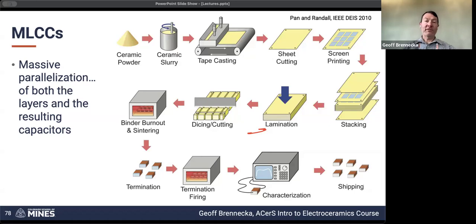And then we throw it in the furnace, just like everything else we do in ceramic processing. There's a furnace step of some sort. So in this case, we're going to burn out the binder as slowly as necessary, because if we just throw it in and heat it up too quickly, then we convert all of that organic binder into CO2 very quickly and create a lot of gas pressure, and we just turn our very fancy multi-layer capacitor into a bunch of powder again, because all that binder burnout has basically exploded it. So we want to do this slowly.